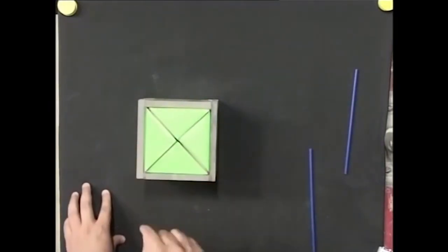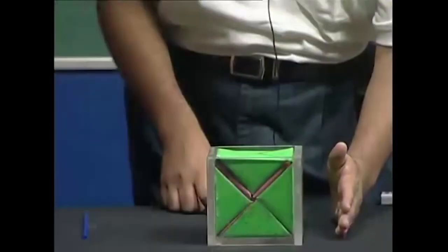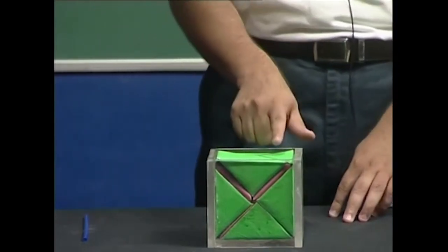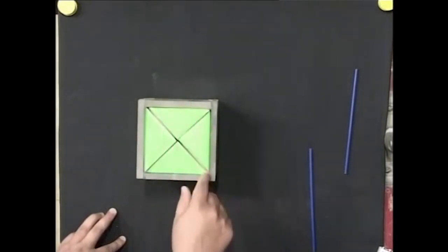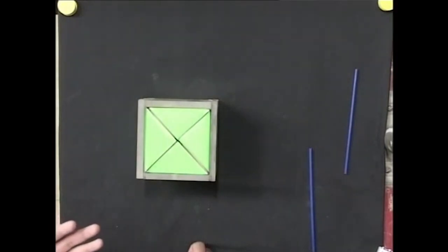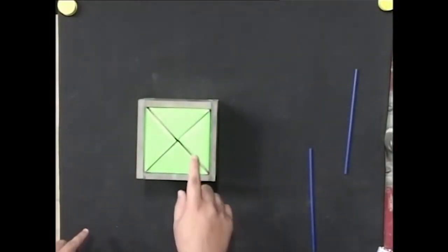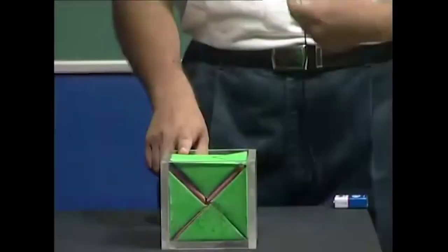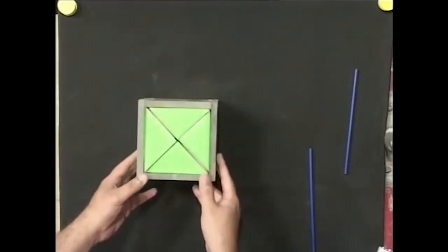This particular octahedral void is shared between this unit cell, the unit cell above it, the unit cell to the left, and the unit cell below — shared between four unit cells, contributing one-fourth. With twelve edges, one-fourth times twelve gives three, plus one at the body center gives four octahedral voids per cell. This matches exactly the four atoms in the cubic close-packed structure, giving one octahedral void per atom and two tetrahedral voids per atom, hence eight tetrahedral voids per cell.